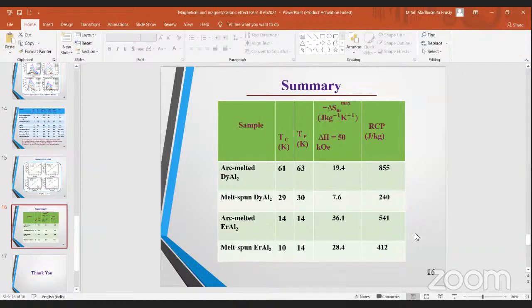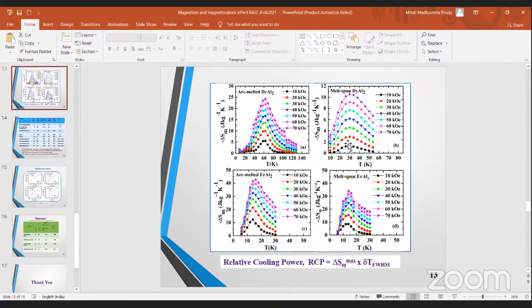Does the property depend on the size of the particle? Yeah, the property depends on the size of the particle, because the TC will change according to the size, and the broadening also will differ in this peak. If the size decreases, then the TC will be maximum for different size distributions of the particles, and the broadening will be there. So for a good magnetocaloric material, we need the maximum of negative of delta SM, also the full width at half maximum. Smaller is the particle, better it is, right? Yeah. Okay. Thank you.